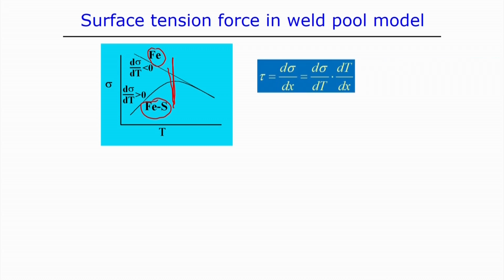That is better explained this way: the shear stress acting on the surface of the fluid can be defined in terms of the first derivative of the surface tension force, because surface tension force is represented by force per unit length. When it is differentiated with respect to length, it becomes a stress value. So, shear stress is linked to the surface tension force, and the derivative of the surface tension force can be written in two components. One is the temperature derivative of the surface tension force, and the second part is the temperature gradient. This decomposition helps to explain the effect of the surface tension force.